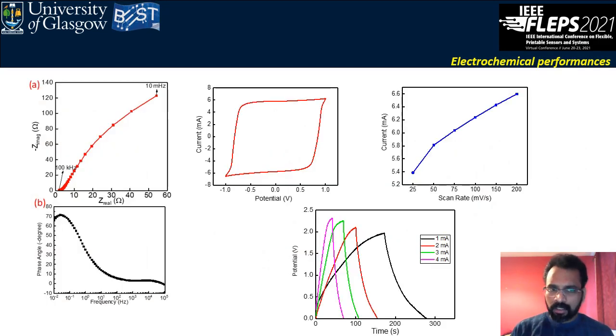Then we characterized the electrochemical performance of this device. You can see here in the impedance spectroscopic analysis and the Nyquist plot that the equivalent resistance of these devices is about 2 ohm. It's a very low resistance, and you can see almost a Warburg impedance, and a phase angle of around minus 70 degrees through the Bode plot. And in the CV analysis we observed an almost rectangular shape, similar to the electrochemical double layer formation of the supercapacitor, and characterized the CV for different scanning rates from 25 to 200. You can see here that the peak current is almost a straight line, which is due to the diffusion of ions.